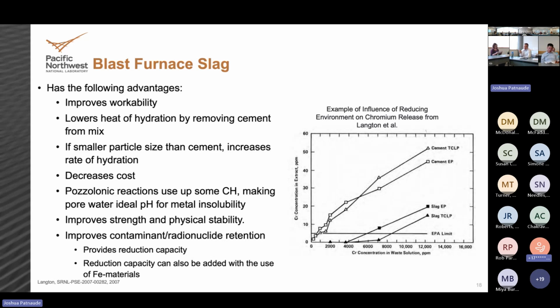Because the slag glass itself, just like the cement, doesn't fully react. In our waste forms, we still see little slices of slag glass. So over long periods of time, that slag continually dissolves, continually releases those reducing species, and helps build in some long-term retention mechanisms to the grout waste forms. So, next slide.